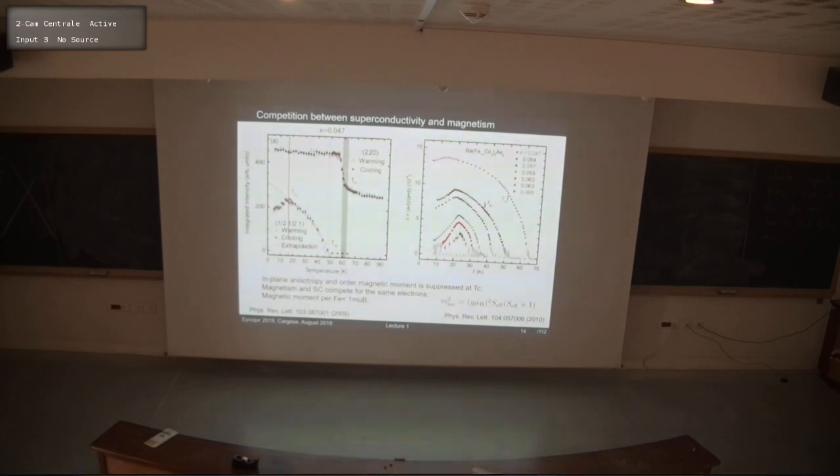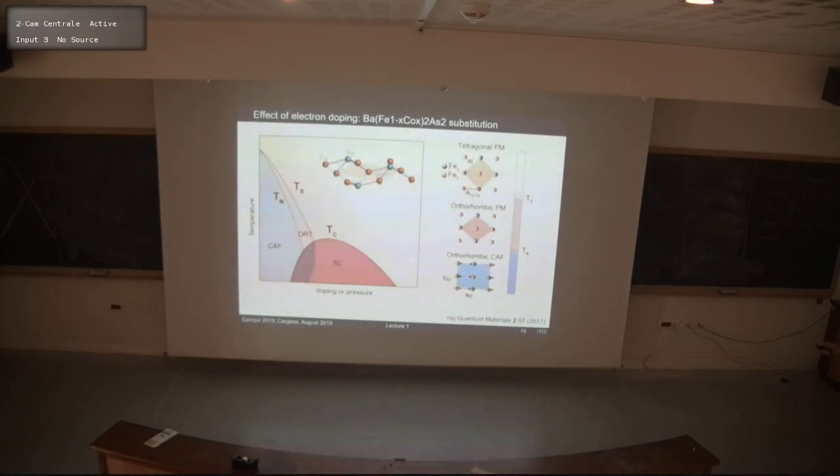One anomaly referring to this material is the magnetic moment detected here. It's extremely small. And this came as a bit of a surprise, because if you think of an iron 2+ in the right crystallographic environment, it should have a very large moment, whereas here the magnetic moment is below 1 Bohr magneton. And I'll mention in a minute more about that.